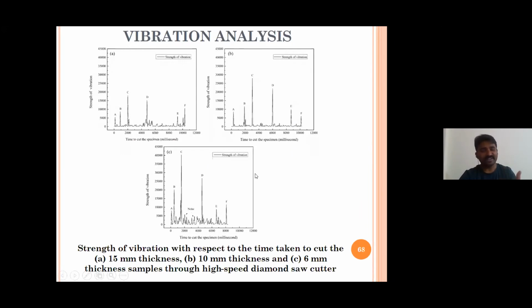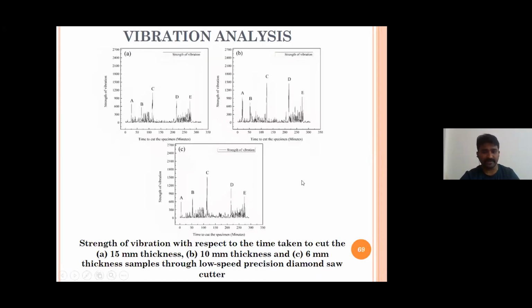You have to have at least 15 mm thick samples or larger. If your SEM allows you to go for 20 mm, 30 mm thick samples, then that is good. But in my case, there was a restriction to go for larger thickness. So I had to restrict myself to only 15 mm. For that 15 mm also, there is some amount of vibration, but it is lesser compared to 10 mm and 6 mm. See here, for 6 mm, there is huge vibration, almost 45,000 strength of vibrations.